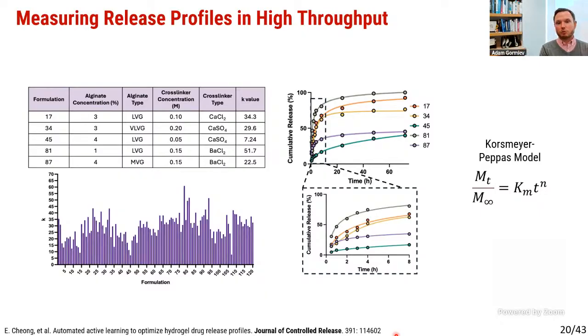So we're modeling every release profile and calculating, based on the model line, this K parameter, which tells you the overall burstiness of the release. Is it more zero order, or does it release very quickly at the beginning? What we're trying to do is minimize K, because the lower the K, the more linear the release profile, the more metered out it gets. The higher the K, the more you get an exponential rise at the beginning, and then it plateaus near the end, which is what you're seeing with this gray line.